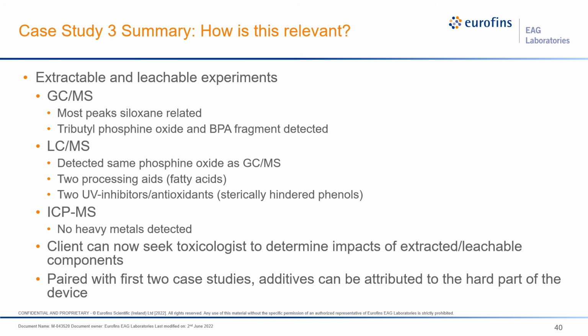So what are the takeaway messages from our extractable and leachable experiments? We're mostly detecting siloxane-related peaks by both GCMS and LCMS. We were able to detect tributylphosphine oxide by both GCMS as well as LCMS. We detected some processing aids or fatty acids, as well as 2 UV inhibitors and antioxidants. ICP-MS did not detect any heavy metals, so now this client can take this data to a toxicologist and determine the impacts of this extractable and leachable experiments. So paired with our first 2 case studies, we can also conclude that these additives are likely attributed to the hard part of the medical device.